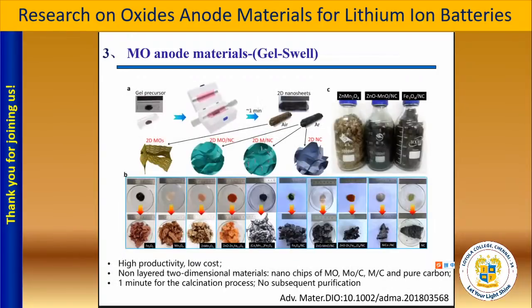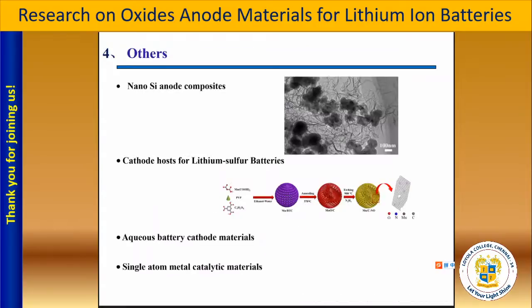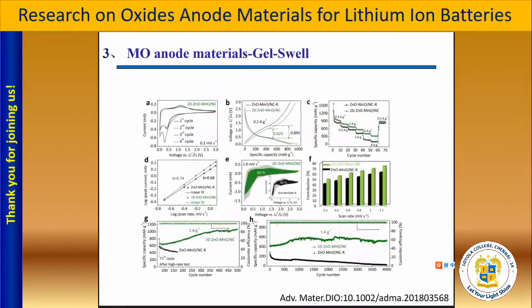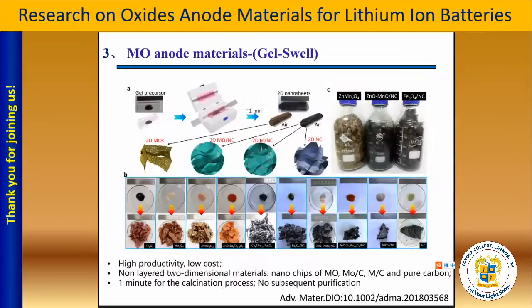Another kind of material preparation I want to show you is named the gel swell. I don't know why the PPT slide will automatically move. We call it gel swell. That means we first prepare the gel precursor, put the precursor into the oven, and in a very short time, about 1 minute, we can get kinds of oxides with carbon.